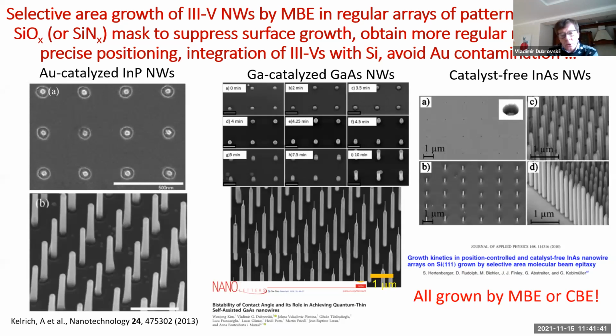So selective area growth has this advantage, as well as, of course, when you process the oxide or nitride layer, you can organize your nanowires in regular arrays by organizing the growth seeds. And nowadays, there are different methods of growing III-V nanowires by the selective area approach. So you can still use gold, like in this case. These are gold catalyzed indium phosphide nanowires grown on indium phosphide substrates.